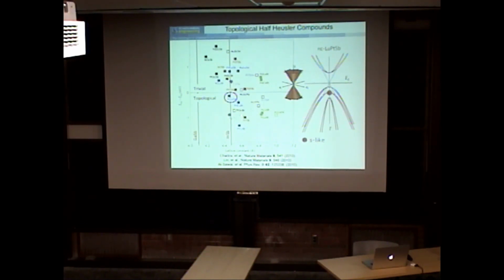So this is basically, the larger the atomic number, you can think of this, the more spin orbit, the more topological it's going to be. We decided to pick platinum lutetium antimony, because it's right on the border between the trivial and topological. And you can see it's closely lattice matched to indium antimonide. So can we grow this material and can we figure out if it's actually topological?